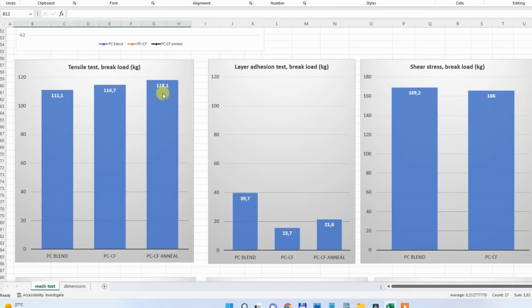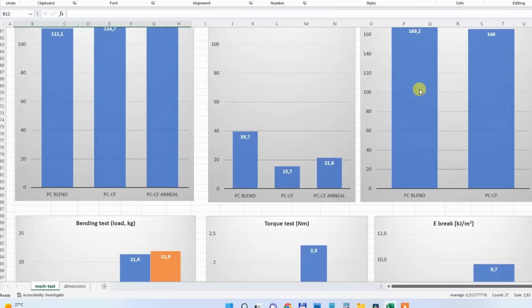Tensile test, very similar values here. Now with the layer adhesion, there is a bigger difference. You can see the scale is similar, but anyway, this is acceptable. With the regular PC blend, 40 kilograms. But 15.7 with the carbon fiber version, this is a very low value. And annealing helped a little bit, but not much. So this is something you have to keep in mind when you choose your printing orientation, for example. Now the shear stress was very similar in both cases.